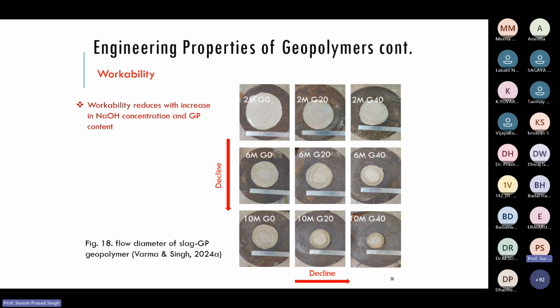This is the workability study. We have 2 molar alkaline solution. G0 means glass powder 0, then we have 20% glass, 30, 40, like this. The slag is replaced by glass, and here we have molarities 2 molar, 6 molar, and so on. As you increase the molarity, the workability reduces, and again, if you increase the glass content, the workability also reduces. That happens due to the effect of angular glass particles on the workability, and as the alkali solution is viscous in nature, as the molarity increases, the viscosity increases and the flow also reduces. This is very common.